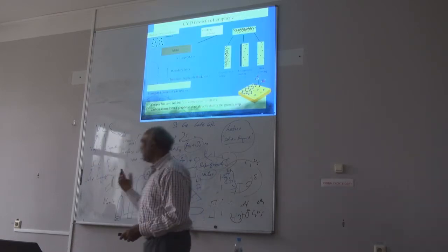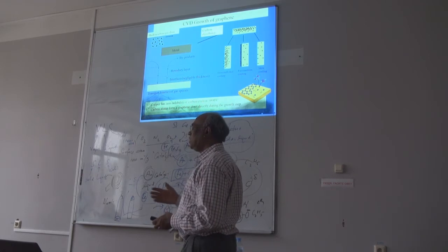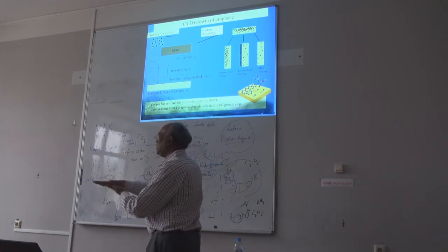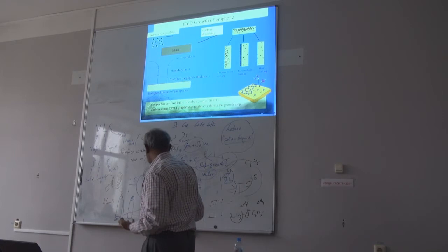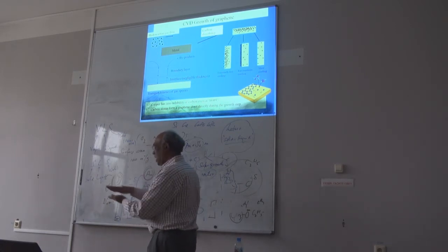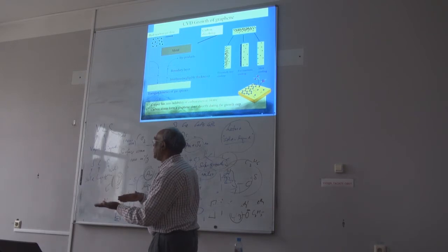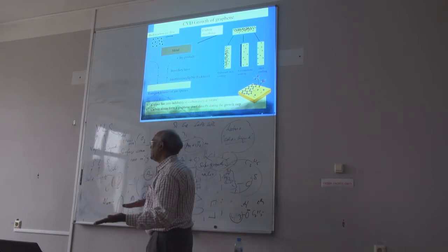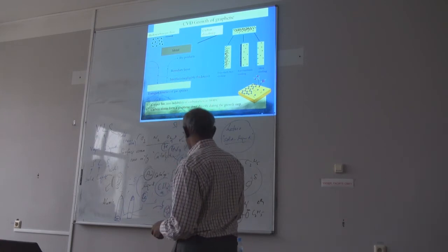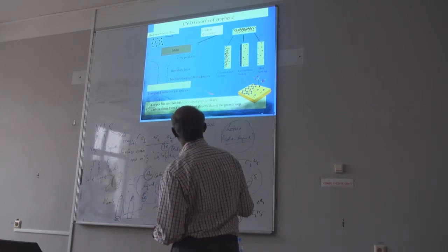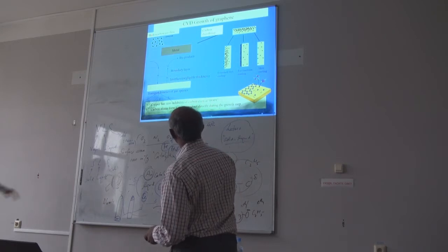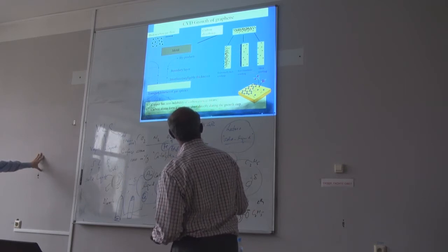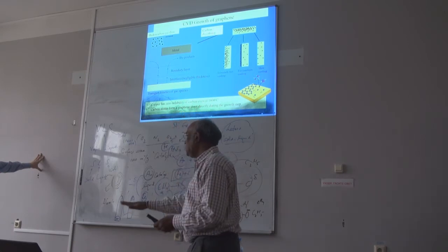Now if you go to graphene, what we need is that we should not have the carbon dissolved into the particle, right? So for that, iron is not good, but gold is, because carbon is not going to mix with gold. So then it will just spread. That's why people started with copper. So if you have a copper substrate, when you introduce this methane gas, the carbon doesn't really mix here, so it just deposits on the surface. So then you can find graphene on the surface.